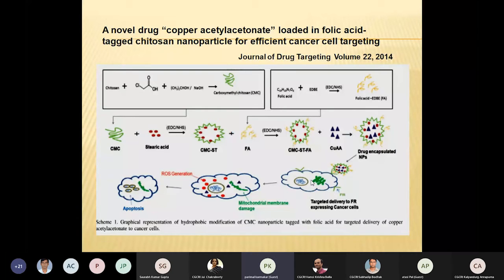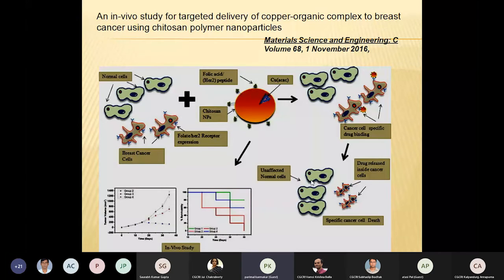And also we used another strategy where chitosan nanoparticle is encapsulated with copper acetyl acetonate, and this coating chitosan is now attached with folic acid, so that they will go specifically to bind to the folate receptor containing cells, mainly the cancer cells, and release the content, because the chitosans can release the content of copper acetyl acetonate and kill the cells. And we have seen that this can interestingly reduce the tumor, and tumor regression is also seen in the case of the BALB/c mice.